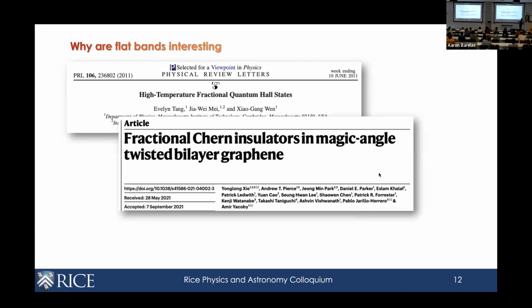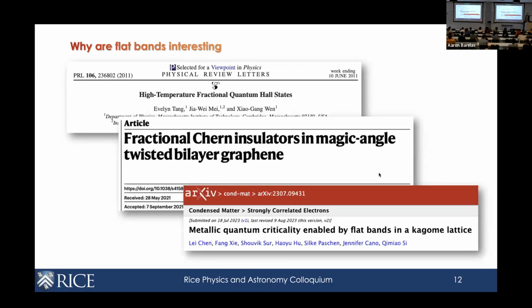This is Yonglong's result, where he observed experimentally fractional Chern insulators in magic angle twisted bilayer graphene. And then most recently in bulk materials, this is the result of Qimiao's group from Rice here, and this is their report of quantum criticality enabled by flat bands in the Kagome lattice. So the bottom line is, when you think about a flat band, it's contributing a large degeneracy across momentum space, which means that it is unstable against many kinds of interactions that will connect this large degeneracy and then lead to emergent orders. So this is a regime that will be very interesting for looking for emergent orders and emergent phenomena.